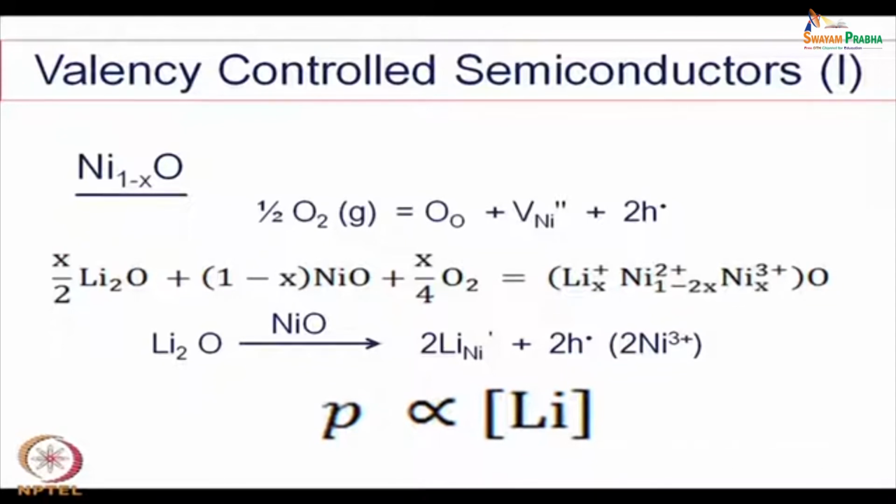So, it becomes more or less temperature independent, except of course the mobility term will change, but the concentration of the holes, the concentration of the charge carrier here, will remain fixed by the concentration of lithium. So, in any particular sample, if we prepare with some percentage of lithium, the conductivity of nickel oxide will remain constant. It will be independent of PO2.